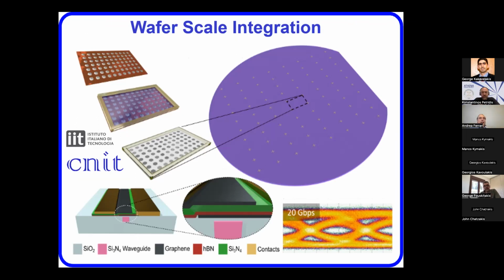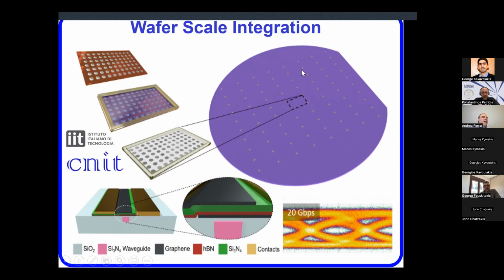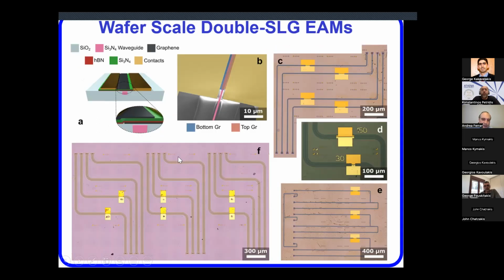it's now really taking off, this field. And last year, as a proof of principle, together with CNIT and IIT, we were able to produce 12,000 modulators on a wafer. So this is 12,000 modulators on a 6-inch wafer. This is really a proof that the technology is working. And maybe you cannot distinguish it on the screen, but there are some patches that are slightly darker, and those are the individual graphene flakes that are all distributed over this very large wafer.